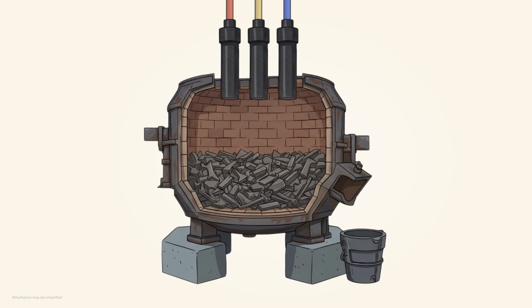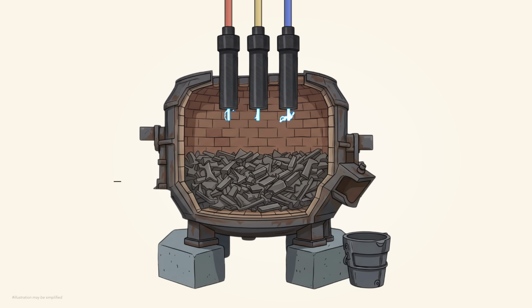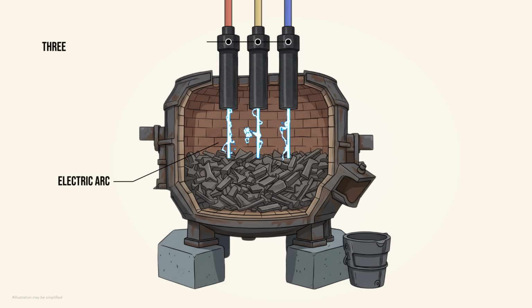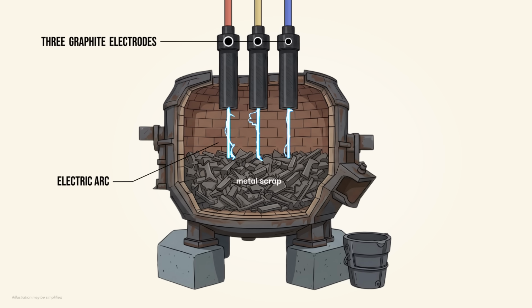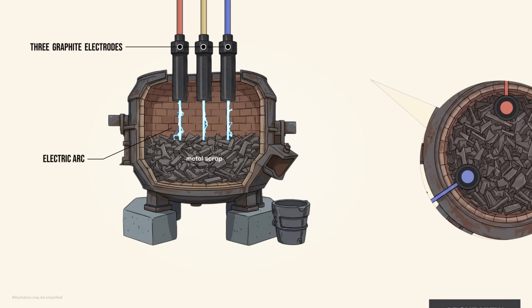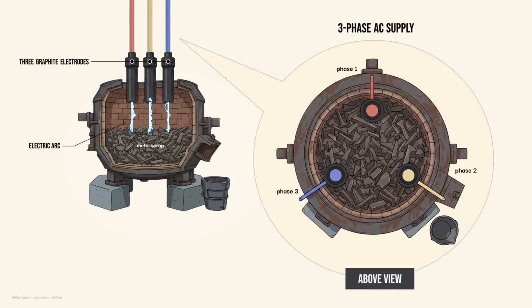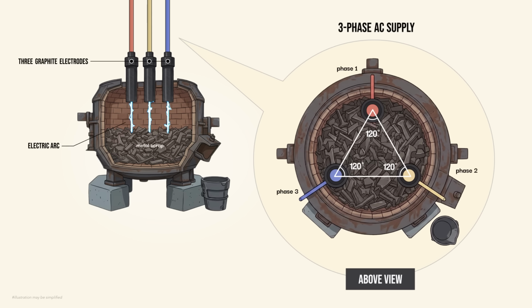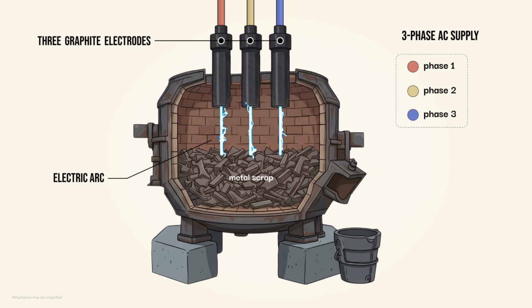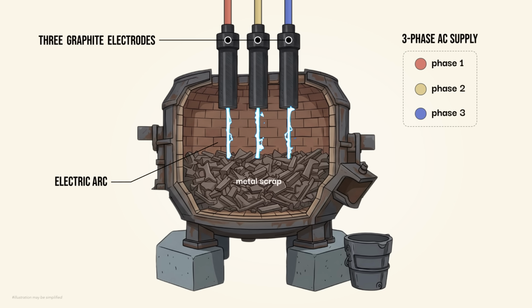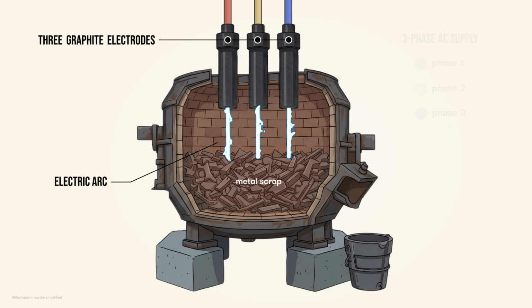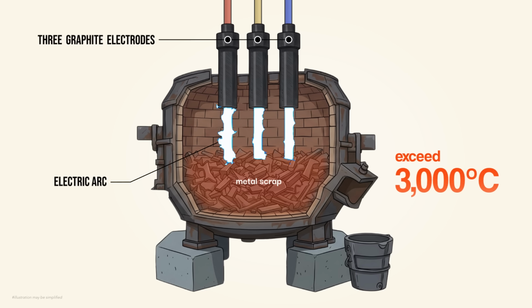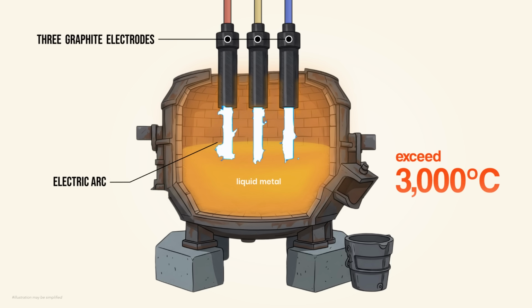The electric arc furnace works by creating an arc between 3 graphite electrodes and the scrap steel below. The 3 electrodes map directly onto the 3 phases of an AC power supply, arranged 120 degrees apart in a triangle. Each one carries a separate phase to ground through the melting steel itself. The arc temperature can exceed 3000 degrees Celsius and is hot enough to quickly reduce solid scraps into liquid steel.